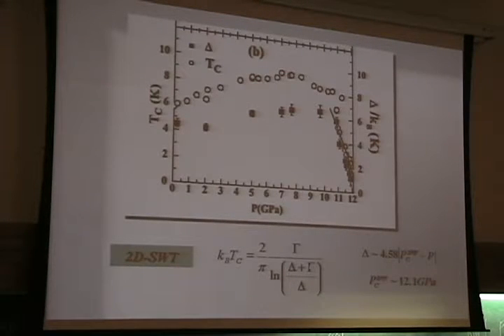Okay, and within this spin wave scenario for a two-dimensional ferromagnetic spin wave, we can get this kind of relation between the transition temperature and the gap of the magnons. Okay, and this could fit our... It's not well shown here, but this could fit well this Tc, the transition temperature near this critical point. Okay, this could describe very well this critical line here, and this is a hint that there must be some reduction of dimensionality in this system, at this critical point. Okay.